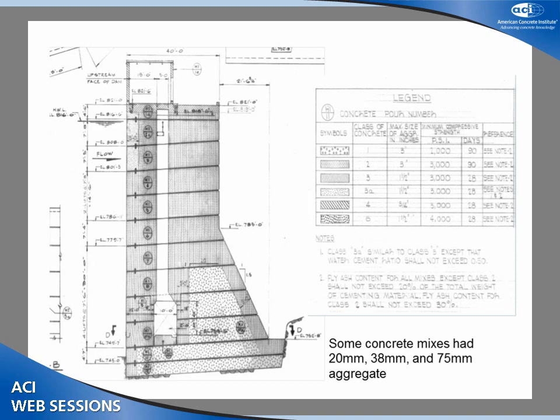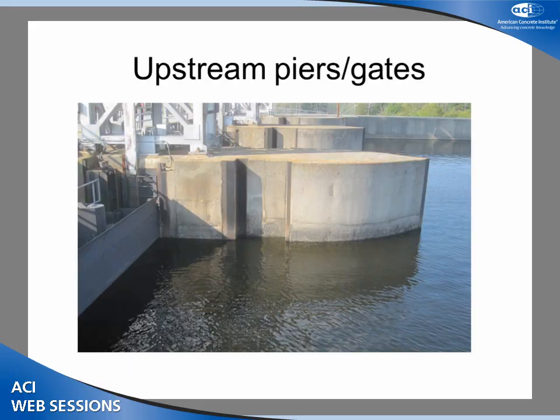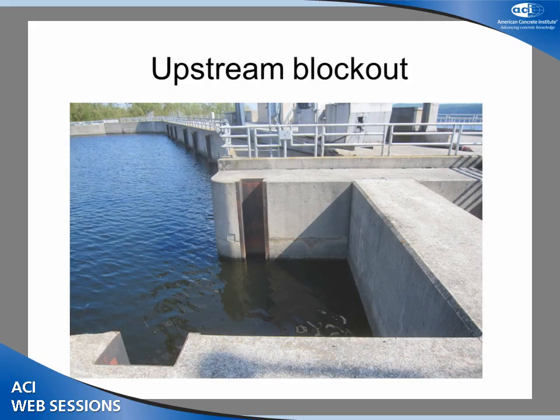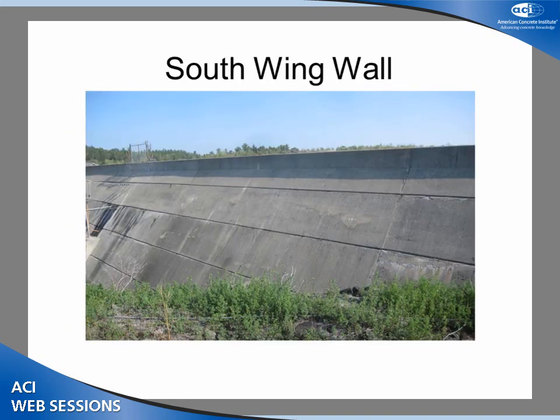So the core concrete, because they're looking at mass concrete and heat of hydration, they don't want to have thermal cracking. So they're relatively low cement contents, low strength. But this thing is now 40 years old. We were up there in 2010 when it was 40 years old, so now 43, I guess. And there's no evidence of ASR damage in the structure, made with a 1.1% alkali cement, but 20% fly ash, and this reactive rock. So here's just the upstream on some of the intake structures, and there's no damage.